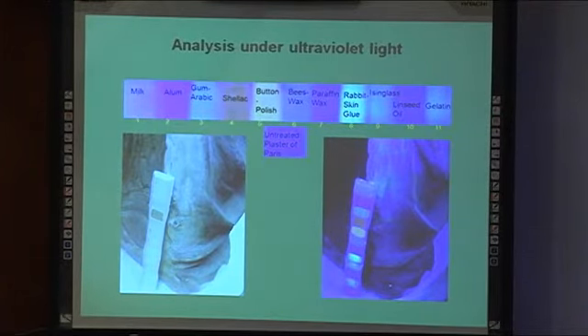It showed that there was at least 2 different coatings on the plaster cast. A green fluorescing layer followed by an orange fluorescing layer. The closest match to the green was beeswax, gum arabic, and rabbit skin. It has to be taken into consideration that the age, concentrations, and number of applications of the coatings tested could differ from that applied to the cast, resulting in a difference in the intensity of their fluorescing.